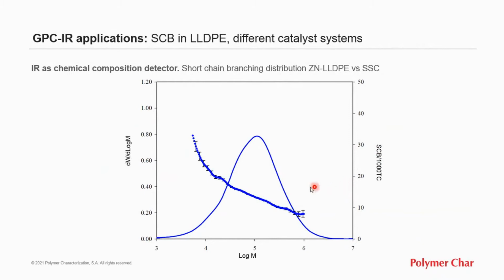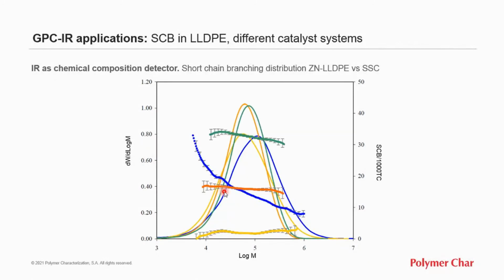Also, the short chain branching trend given by the IR helps in identifying the catalyst system or studying the catalyst. Here we see GPC-IR analysis of Ziegler-Natta LLDPE showing a clear drift in short chain branching along the molar mass distribution. There is a lower number of short chain branches in high molar mass, and there is a trend of increasing short chain branching towards lower molar masses. This is in contrast to the uniform comonomer incorporation of single-site catalyst products. So we see three different single-site catalyst polyethylenes, with different levels, but they are rather uniform.